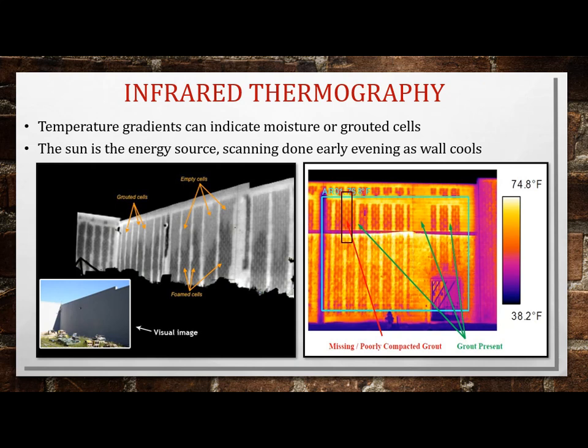So with infrared thermography, you go out at 6 or 7 o'clock at night, as the wall is cooling off, thin areas cool faster than thick areas. And so you scan it with the infrared thermography gun, which used to be very expensive, and now you can get a good camera under $10,000. And so one of the uses is to determine if the cells are grouted or not.